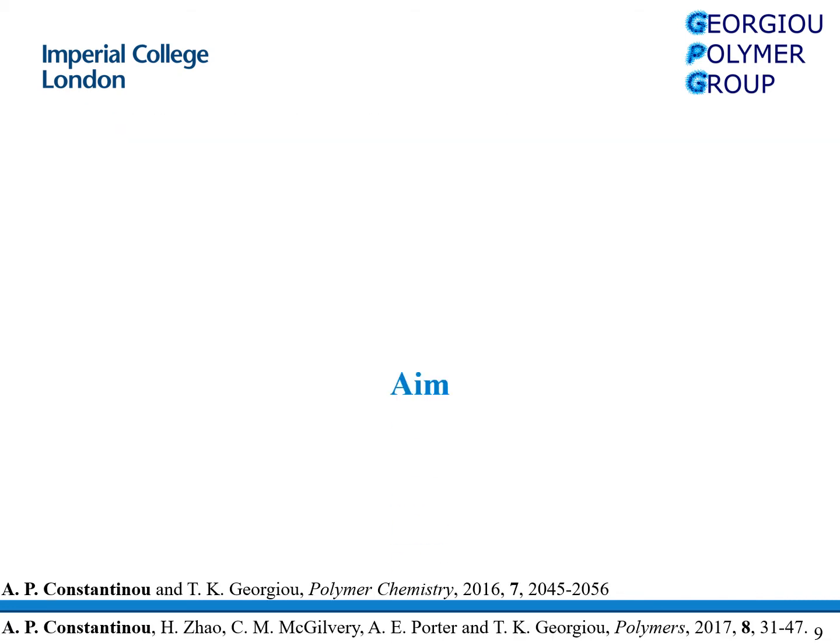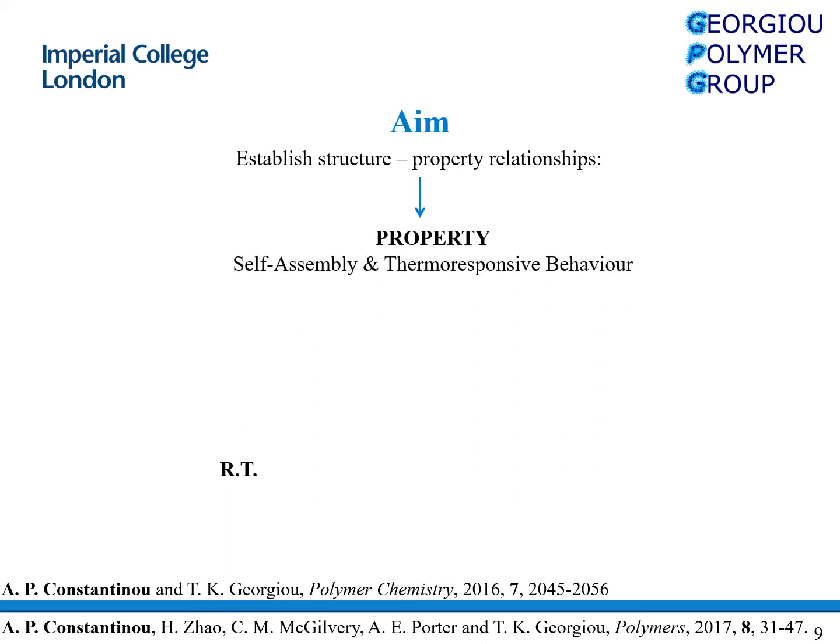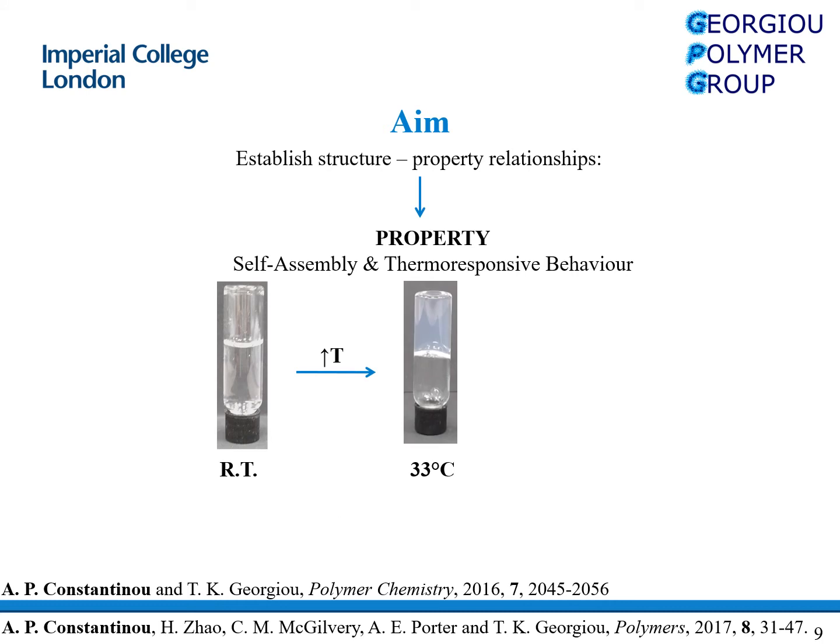After synthesizing the polymers, I was dissolving them in water in order to investigate the self-assembly and thermoresponsive behavior. In terms of thermoresponsive behavior, for example here, this polymer solution is soluble at low temperatures. When it's heated up, it forms a transparent gel. Then depending on the gel, it might become cloudy upon further temperature increase.